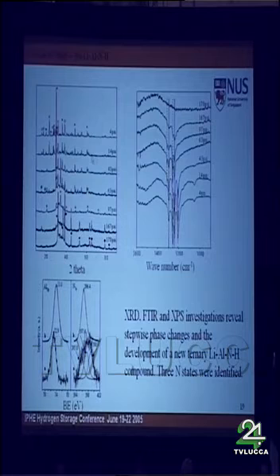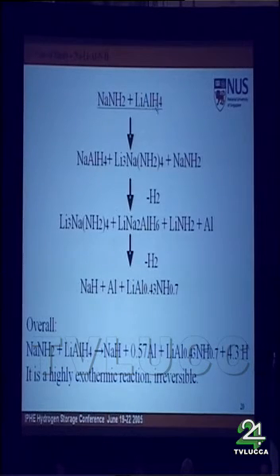By summarizing these investigations, we realize there are a few steps in the chemical reaction. The starting materials are sodium amide and lithium alanate. At the very beginning, there's cation exchange between the amide and hydride. You can see after a certain period of time, the lithium alanate changed to a sodium alanate. And in the meantime, ternary amide is formed.